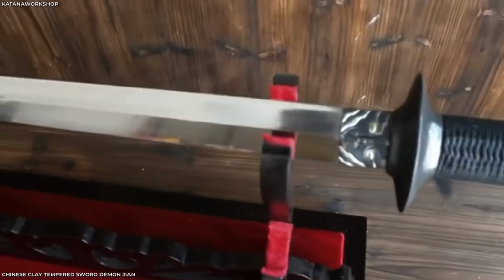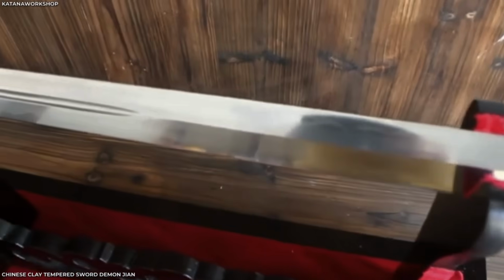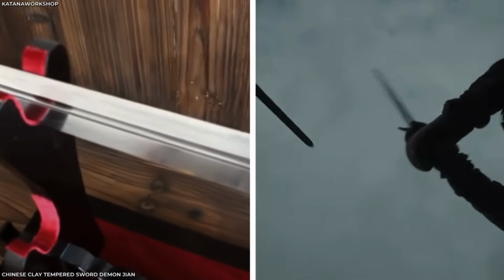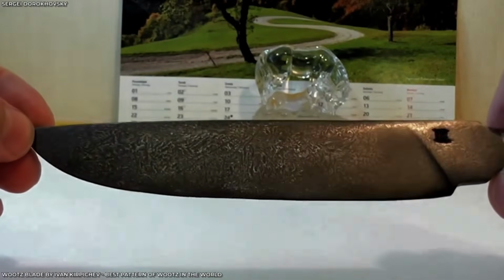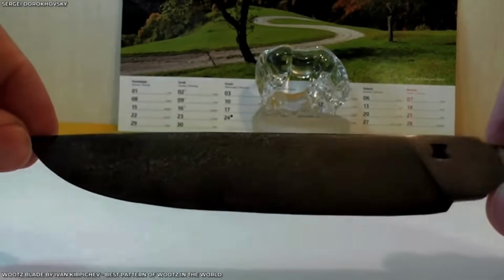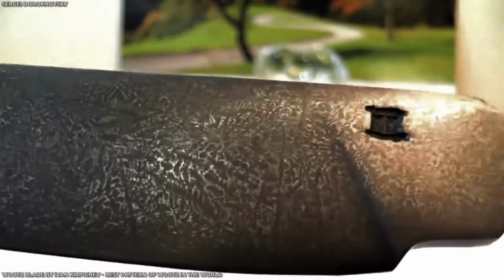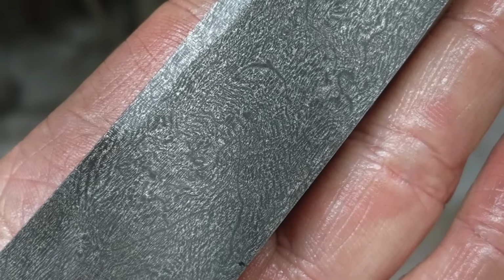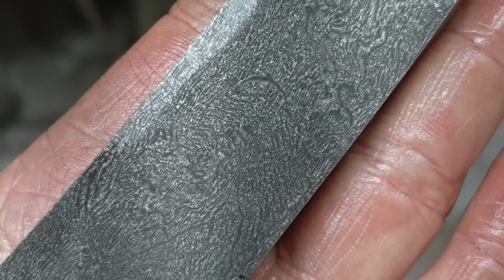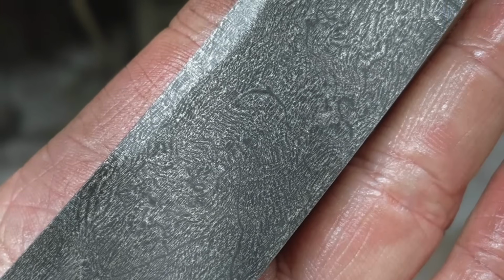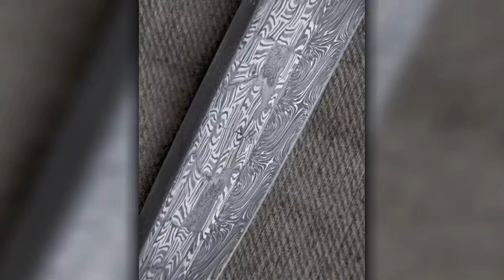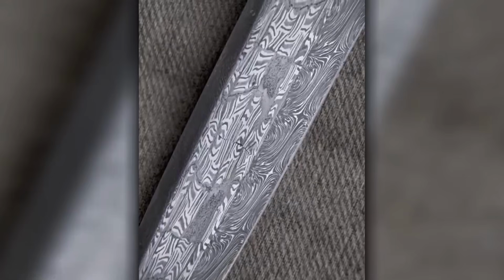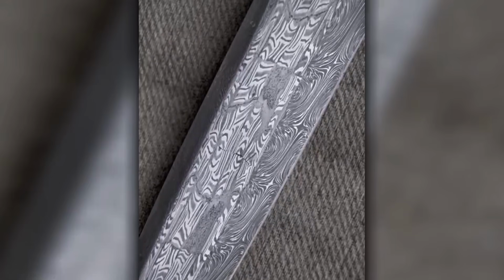The steel was harder than it had any right to be, yet it remained flexible enough to forge into thin sword blades that could absorb the shock of combat without cracking. When those blades were polished and etched with mild acid, the surface revealed the visible watered pattern, alternating bands of light and dark steel flowing across the blade like ripples on a pond. This was not decoration, but the visible signature of the metal's internal structure.